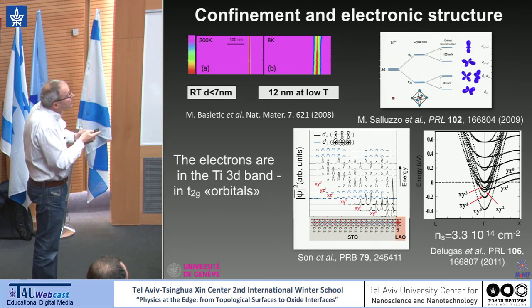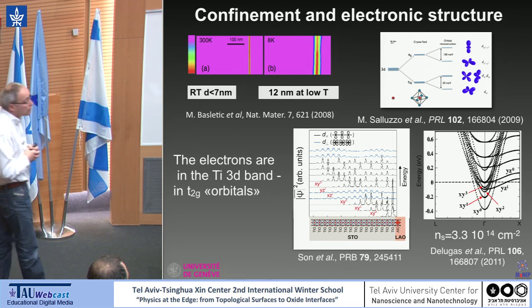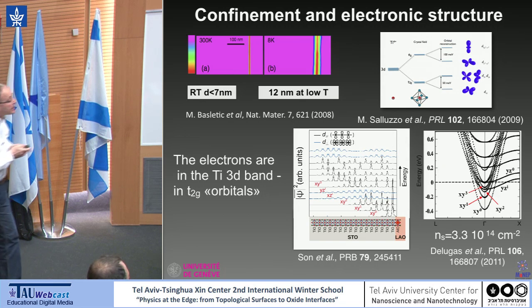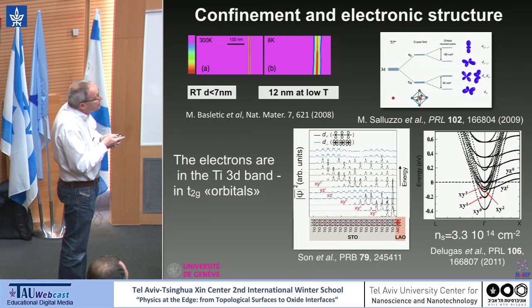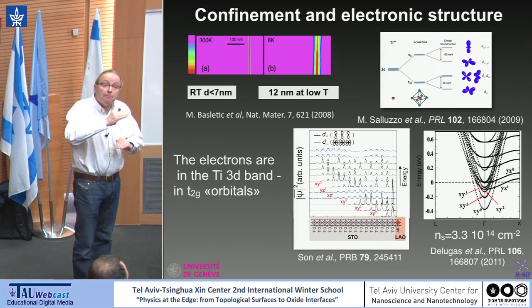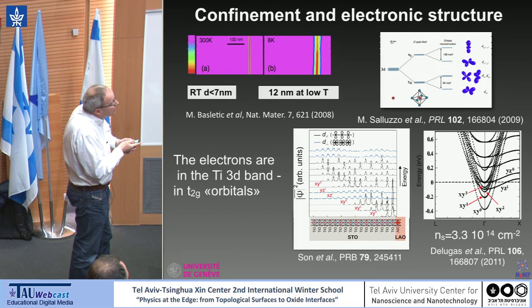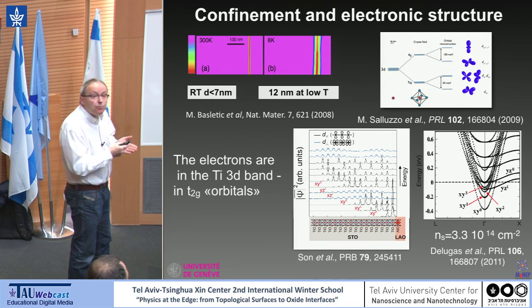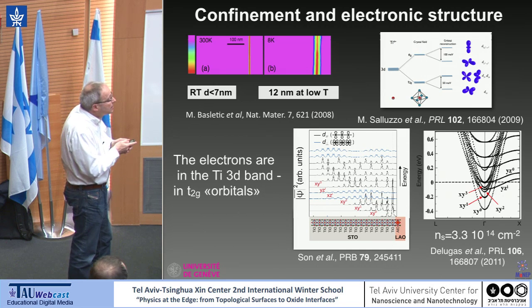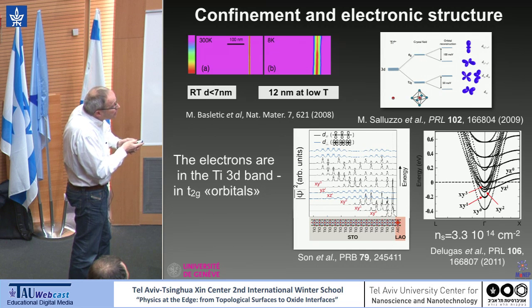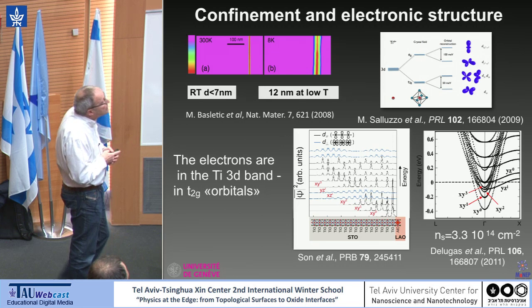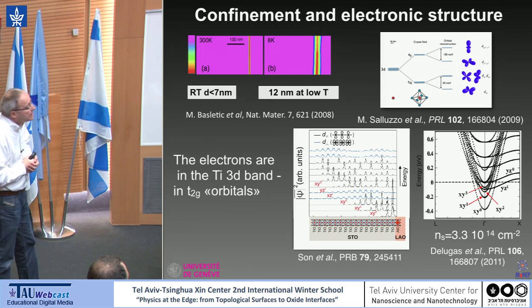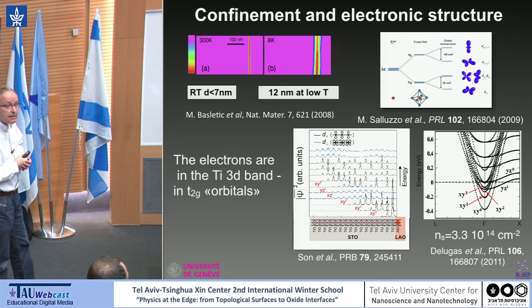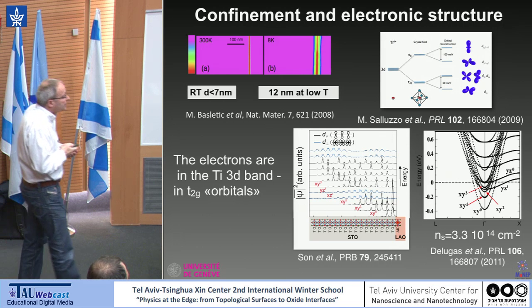And this splitting was first observed by Marco Saluzzo and co-workers experimentally. And you see here electronic structure calculations, which show that because of this confinement, you start to produce subbands. And you see here 1, 2, 3 xy subbands, so light bands. And then only at some point you start to see the xz and yz heavier bands. And this will be important a little later.